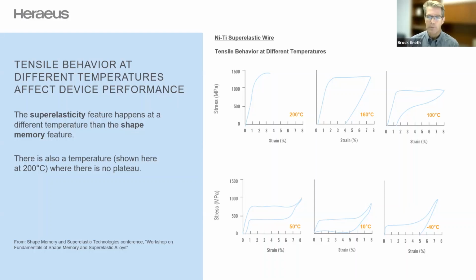we've already talked about. And so if you pull it to 8%, it goes along this loading plateau, you get a lot of movement at the same constant force. You release it, it drops down to the unloading plateau and again returns to 0, it bounces back. And as we've discussed, if you take this wire and you drop it into a dry ice alcohol bath, you will get this shape memory effect. The same material will kind of behave in a shape memory way because you've lowered the temperature.